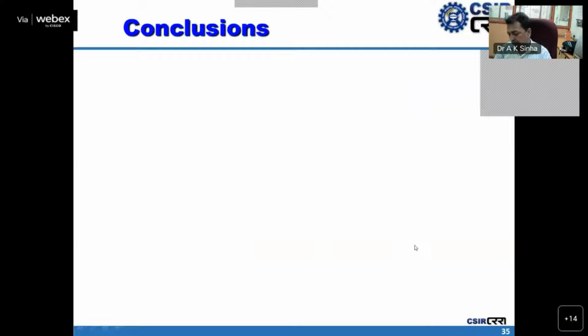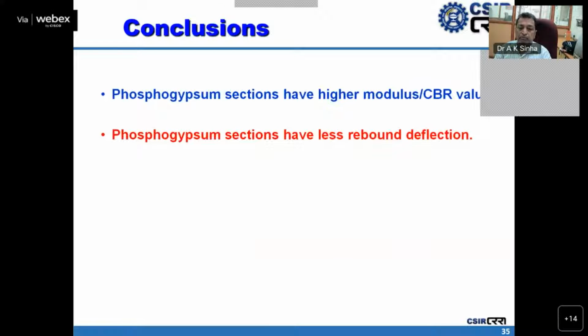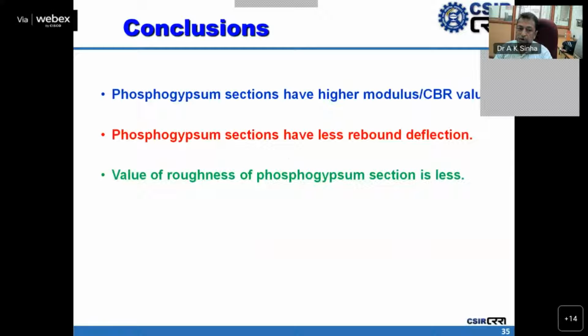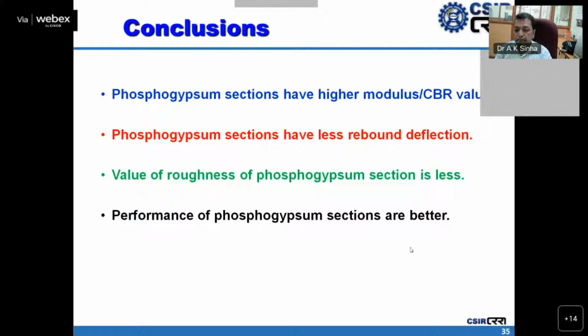From this, we can say that the behavior of phosphogypsum as an embankment material, as a subgrade material, or as a granular subbase material is good, or we can say it is better performing than conventional sections. The roughness parameter is less than the conventional section. Rebound deflection is also less, and the modulus and CBR values obtained from the experimental section are more than the conventional section.